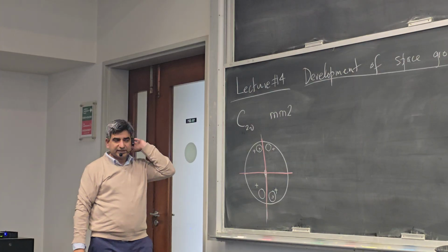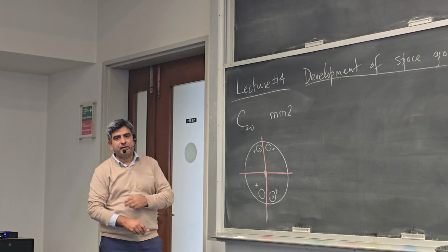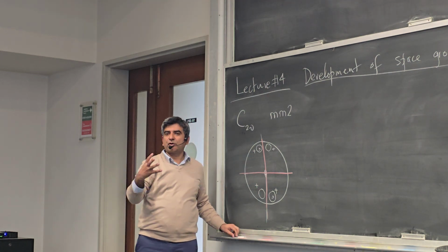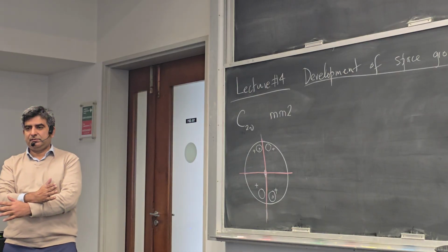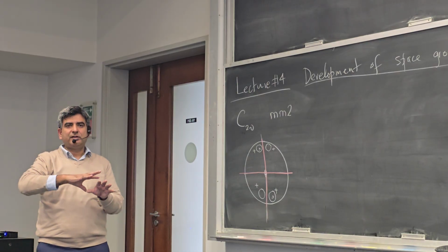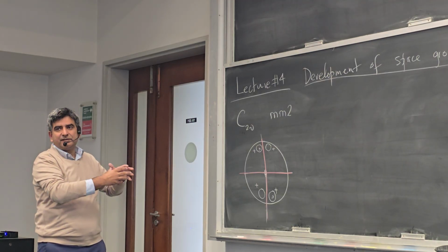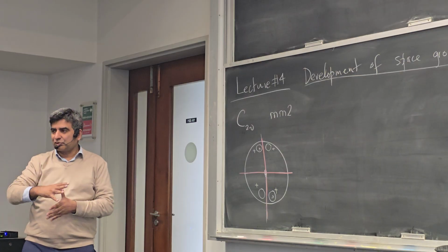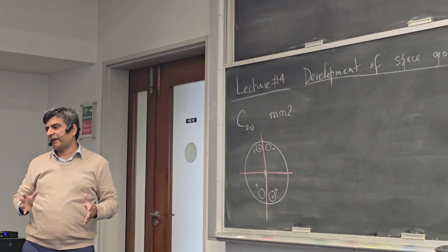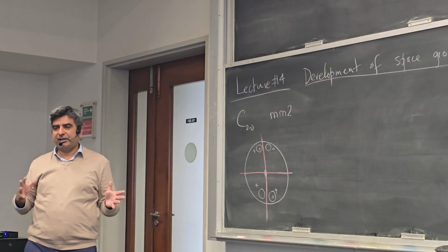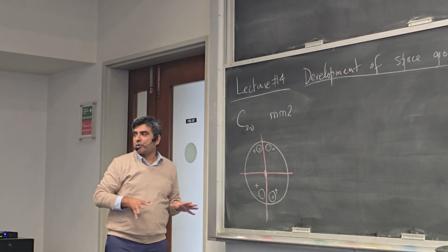So this is the nomenclature of this point group, MM2. And we already know that this belongs to the orthorhombic class because there are two mutually intersecting mirror planes. By definition, if you would draw a unit cell which has the same symmetry elements, we could draw an orthorhombically shaped cell. 3 angles, each one of them 90 degrees, and 3 different sides, A, B, C, they're unequal, right? So this is what we've already seen when we developed point groups.